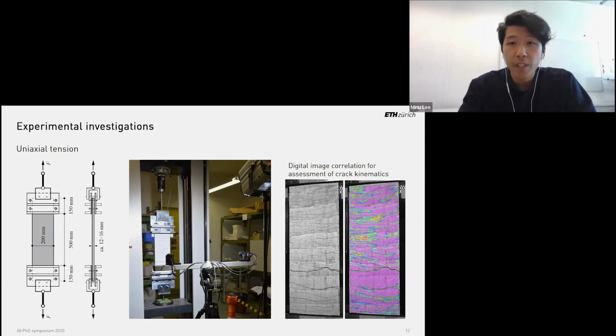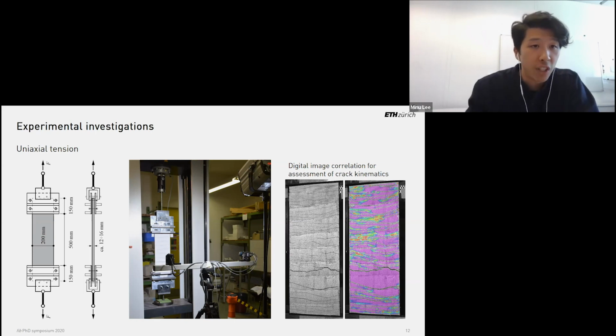To study the structural performance of this non-standard reinforcement, we conducted some experimental investigations with uniaxial tension tests on flat concrete sheets to assess the load deformation behavior but also the crack kinematics, where we use digital image correlation-based measurements. The specimens had a thickness between 12 and 18 millimeters, and they all had one single layer of coated textile in the middle of the cross-section. The test setup can be seen in the middle, where the specimens were clamped in plates and then attached with hinged boundary conditions to the testing machine here. Here you can also see the two cameras that we used for the digital image correlation.